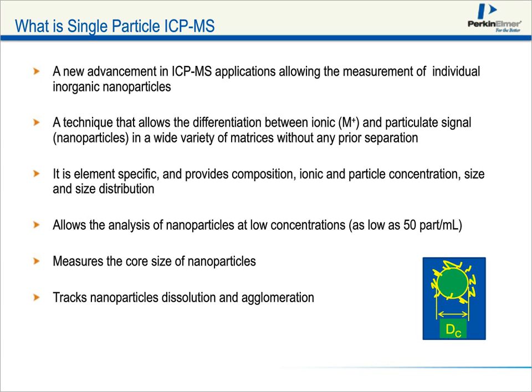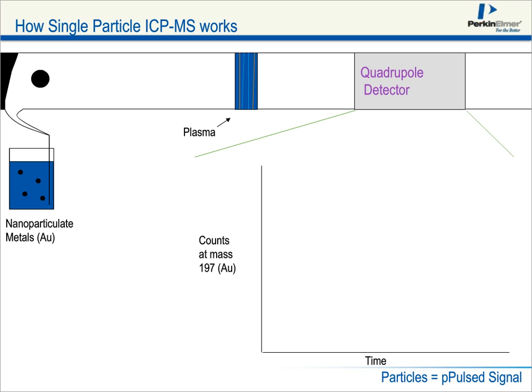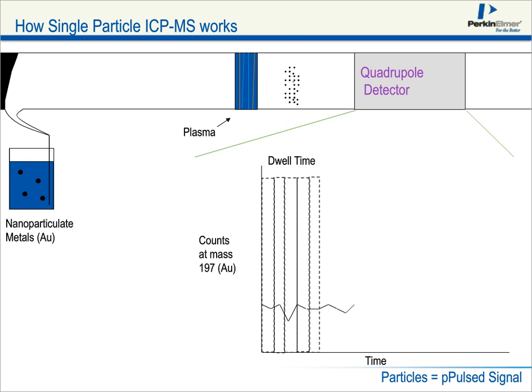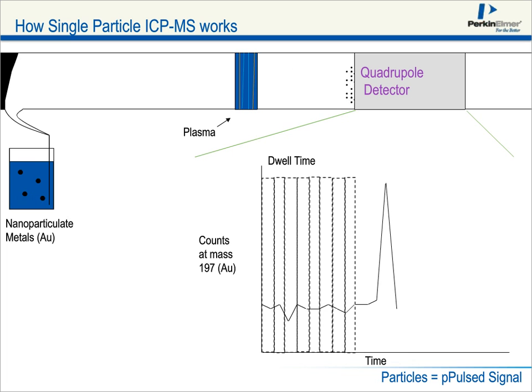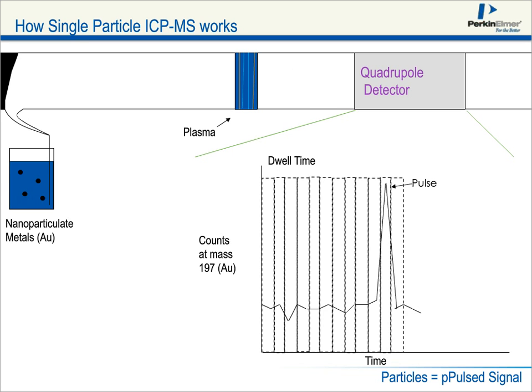So in the cartoon aspect, this is how the single particle ICP-MS works. We're going to be aspirating a solution of nanoparticles. As the particles go through the plasma, it's going to create an ion plume or a pulse. Mainly it's a cloud of ions all condensing together. And when this cloud of ions gets to the detector, we're going to be getting a spike. And this spike is really the science behind the quantification of the size of the nanoparticles.